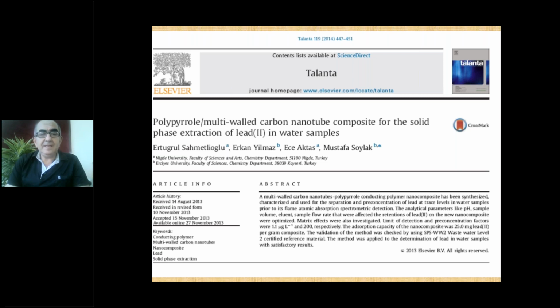prepare these materials by using different methodologies. This polymer plus carbon nanotubes we prepared, then we characterized these materials by using different instrumental techniques like scanning electron microscope, infrared spectroscopy, BET surface area and others. Then we used these materials for solid phase extraction of lead ions, and we have successful results. We have quantitative results for the preconcentration and separation of lead ions by using these materials.